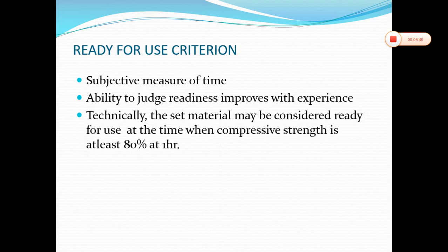By this you can understand, when you pour a cast in an impression, you have to separate it only after 45 minutes to 1 hour, not before that, because by the end of 1 hour it gains a strength of 80%, so that when you try to separate it, the cast will not break. And also final setting has taken place. Before that, if you try to remove it, it has not got sufficient strength, and in the process of handling, it may break.